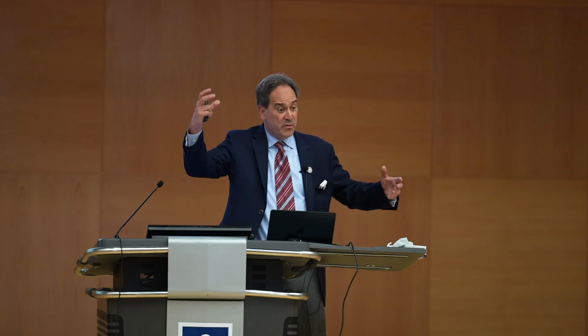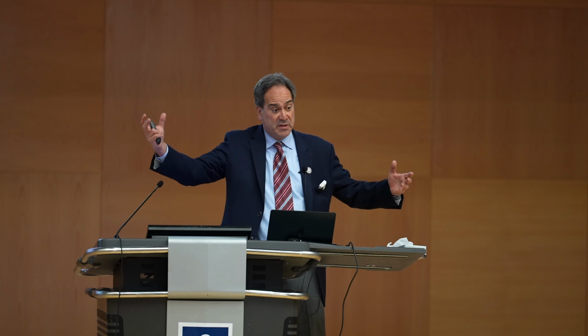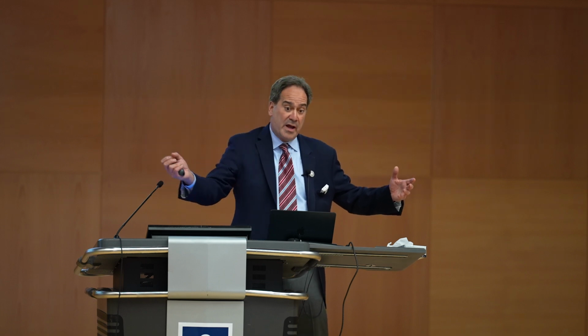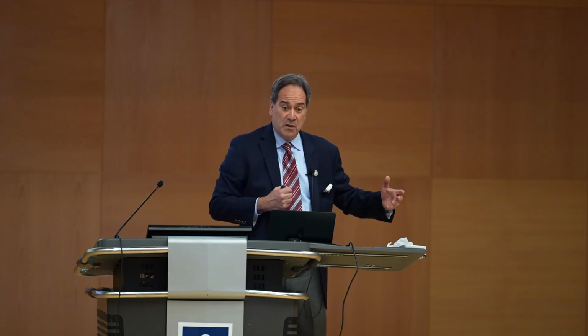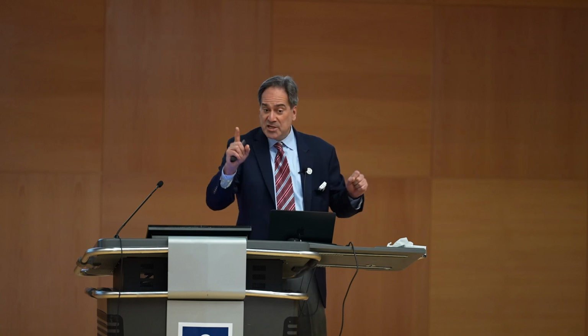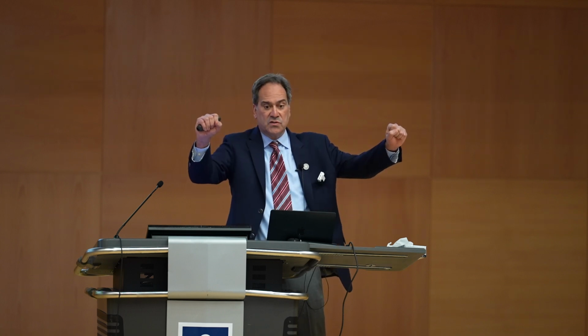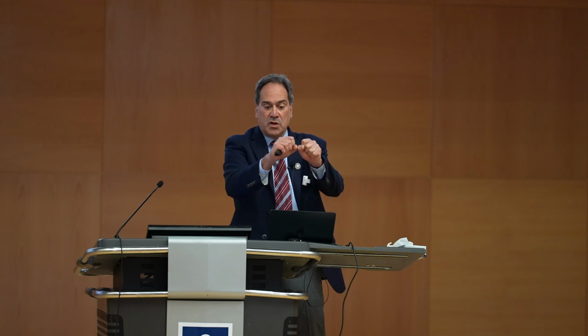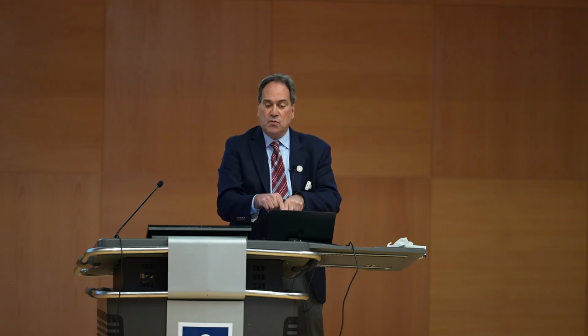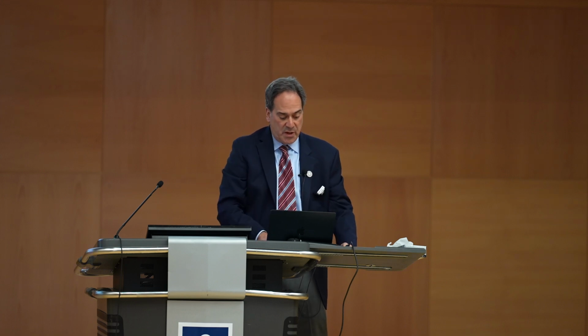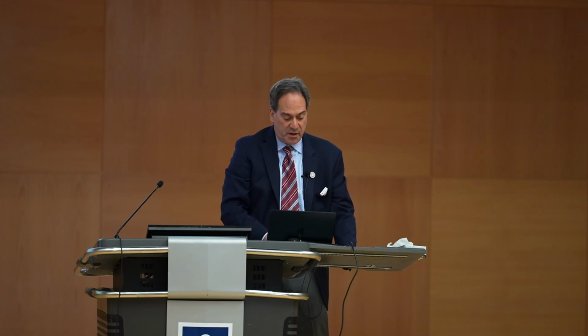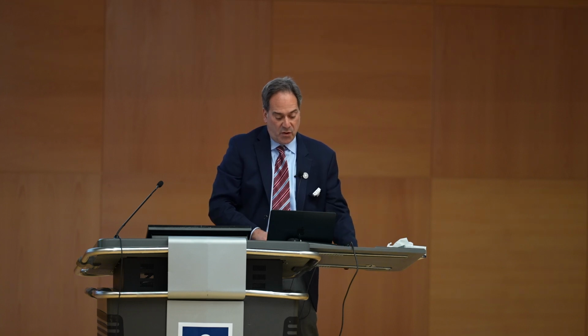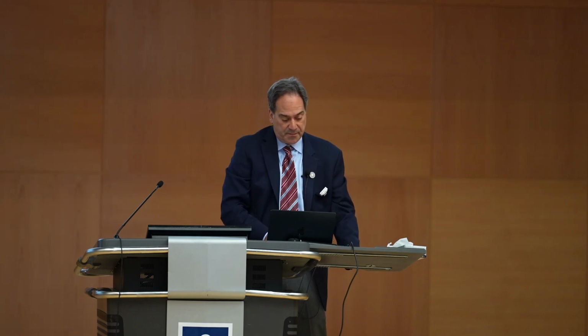So Ostwald ripening, remember, is where big particles grow at the expense of other particles. These particles dissolve and their atoms go in to form the larger particles. You're going to watch that occur. It's actually different from a process called coalescence, where two particles come together and merge. Both are occurring here, and that's one of the interesting fundamental things you get out of this. You can actually track trajectories, and you'll see this as I play the movie, which are just many frames put together watching the growth of a gold particle.